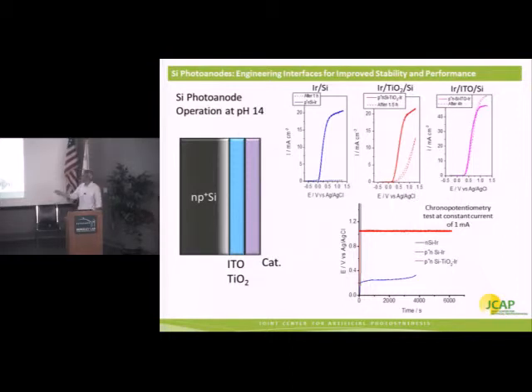So we've tried this recently where we have, in this case, a PN junction in silicon. So charge is separated below the surface of the silicon by an electric field that we generate by changing the impurity concentration in the material. Onto the surface of that, we've deposited either ITO, in this case via sputtering, or TiO2 via ALD or sputtering. And on top of that, we've placed the catalyst. Now, this is a proof of concept, so we used iridium. Again, this is not one of the catalysts that we want for a JCAP device, but it's a highly efficient catalyst that will allow us to diagnose problems that we may be having at lower lying interfaces in the system.